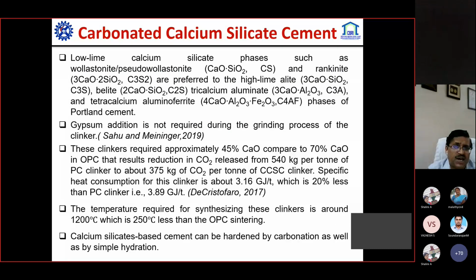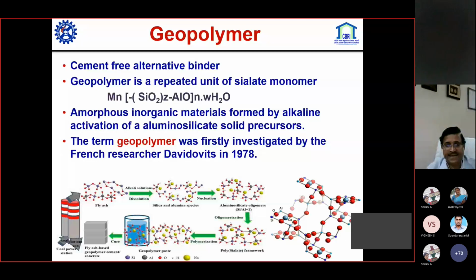And another is the carbonated calcium silicate type of cement. Again, it is a low lime calcium silicate phase, and gypsum addition is not required during the grinding process of this clinker. And overall, the clinkering temperature is around 1200 degrees centigrade, which is 250 degrees centigrade lesser than ordinary Portland cement. It means overall we have sustainability aspects to look for other types of cementitious binder in the country, or our approach should be like that.